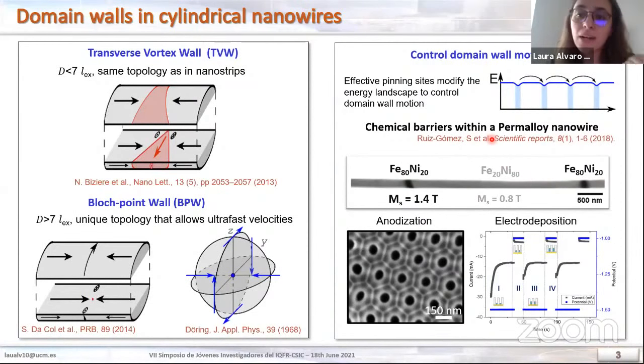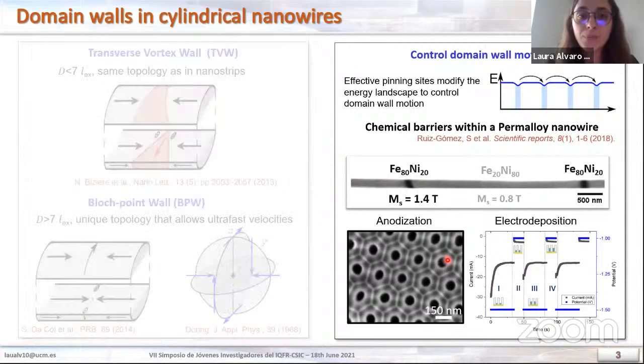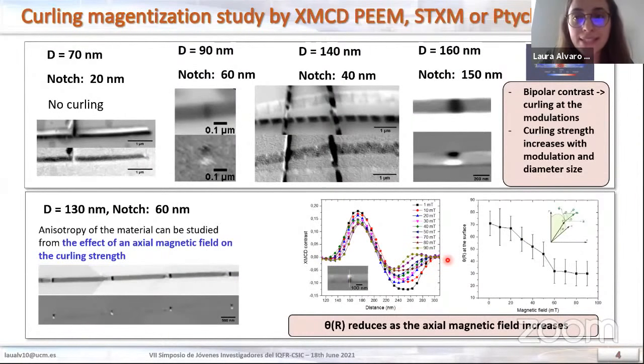In this case, we're using a nanowire made of permalloy with chemical barriers of inverted composition. So these nanowires are grown by single-bath electrodeposition using voltage pulses. Once we have synthesized these nanowires, it's time to do the three-dimensional magnetic characterization. To do that, we make use of X-ray facilities in the synchrotron. In this case, I'm going to show images of PEEM, STXM, and ptychography, where we can have access to the volume information of the magnetization.